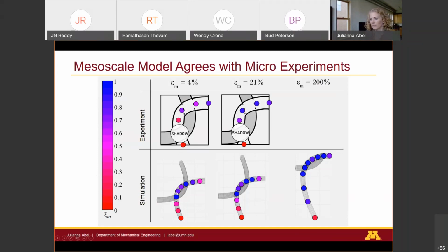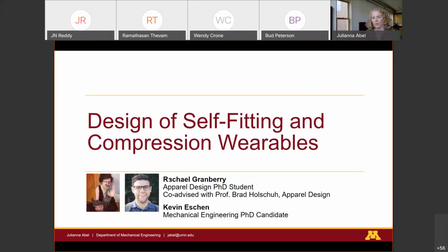And this was great. We developed a model based on finite element methods that captures both the nonlinear geometry and deformations and the nonlinear material. And we see the exact same thing through this model. So now not only are we able to predict the macroscale behavior, we're able to know the local stresses within the material. This is really important because when you're working with shape memory alloys, you want to minimize the strains, because if you go to strains above 4 to 8%, you're going to get decreased repetitive performance. So now we understand our strain distribution through our material, and we can tune our architecture to achieve the performance we need. And so now we're going to move on to how we're using this information.